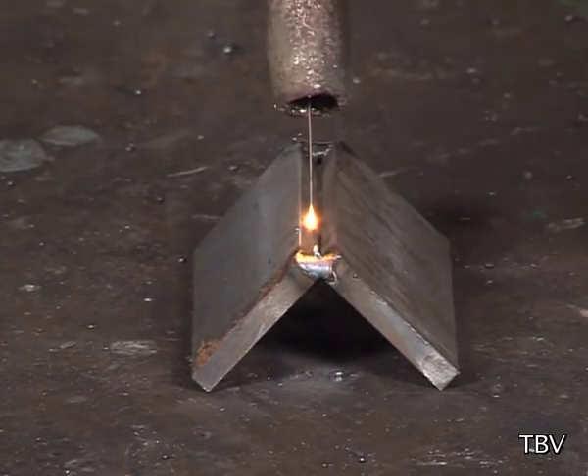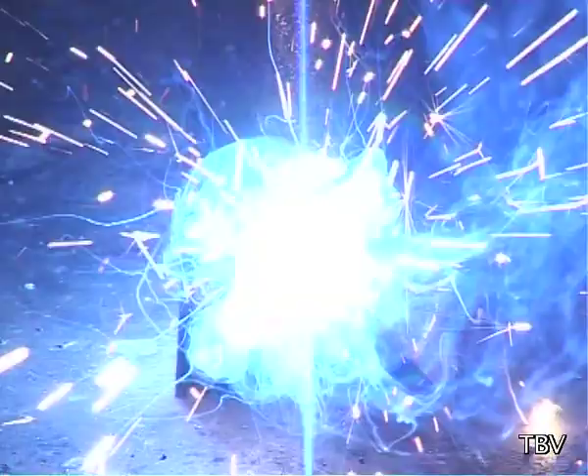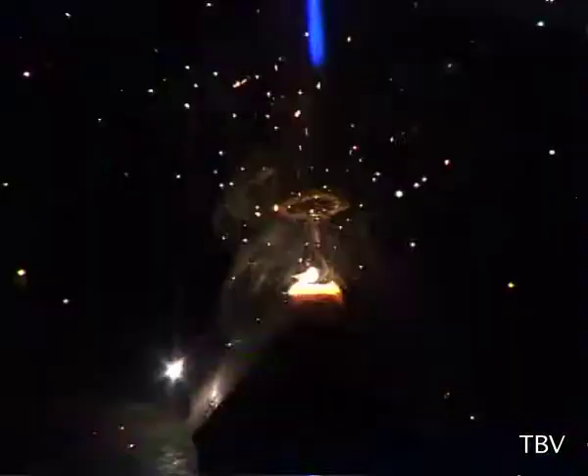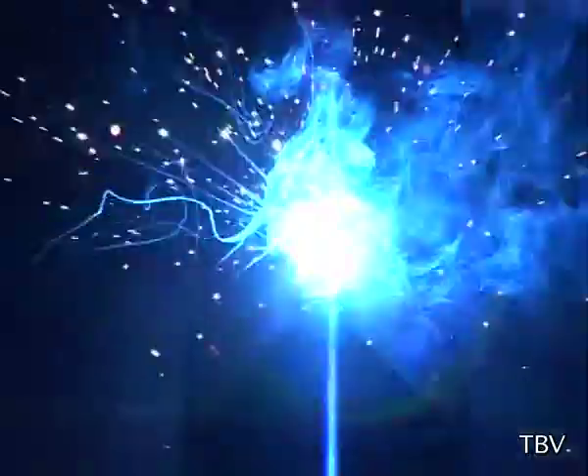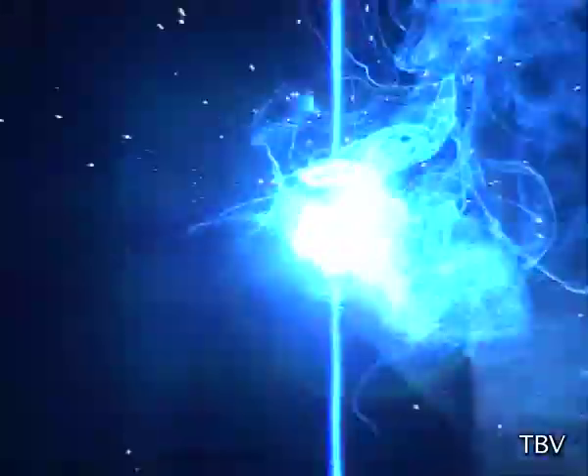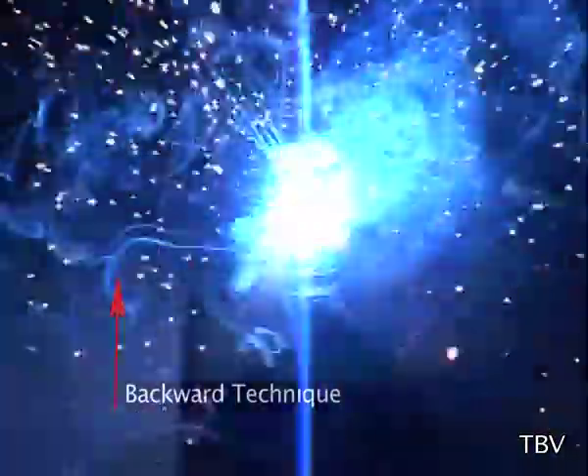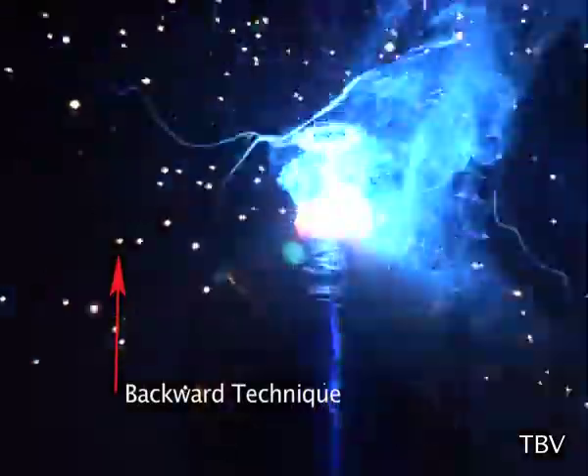Hold the gun perpendicular, or 90 degrees, to the joint and strike the arc at the tack, which is also 90 degrees. Move the torch from one end to the other end of the joint in flat position, maintaining the angle of the torch at 10 to 15 degrees towards the direction of travel. Weld the full length of the workpiece by filling the material in the weld area, moving backward.